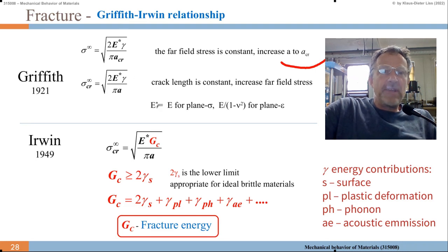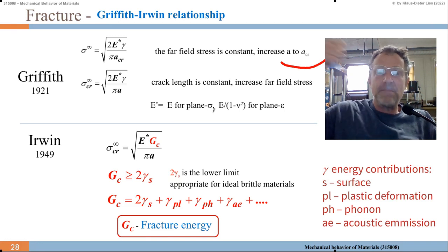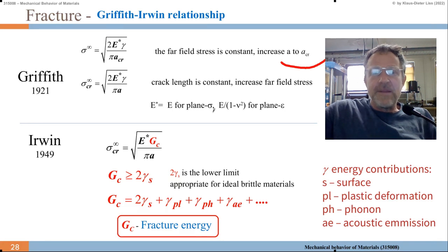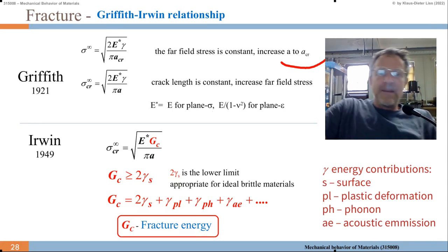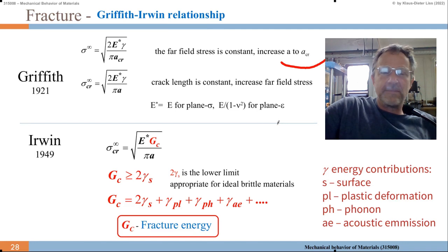Now what do we put in for E? We put in E star, which is E for the plane stress situation. We've had the plane strain and plane stress formalisms in the two-dimensional formulation, remember the Airy function. For E star, we put in E over 1 minus nu squared for the plane strain condition.